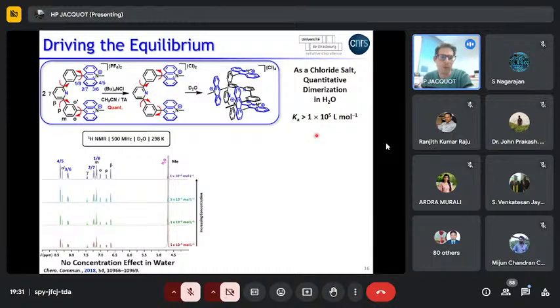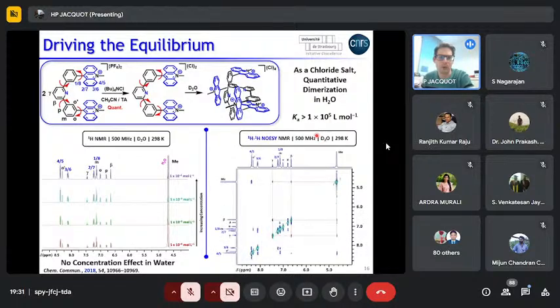So one proof that we have this dimer in solution was provided by the NOESY spectrum. So we can see some through-space correlations between what I call the gamma proton and the methyl, beta proton and the methyl. So gamma and beta protons of the pyridinium core and the methyl of the acridinium core. So if you have a NOESY correlation, this means that they are close in space, and this is what we expect from the solid state structure.